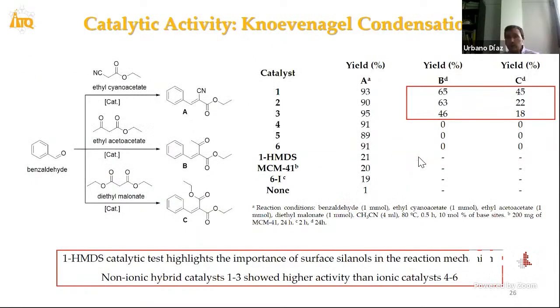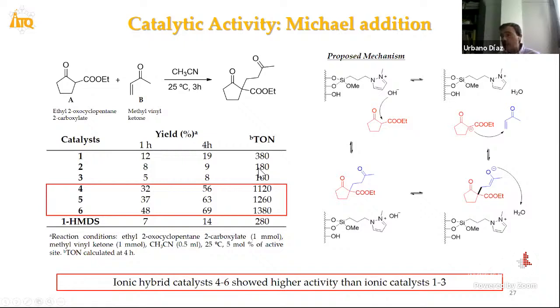The catalytic activity was tested for this type of base hybrid materials, confirming that the non-ionic hybrid catalysts exhibit very elevated yield and conversion in this type of Knoevenagel condensation, depending also on the methylenic group used as substrate, and identifying the importance of surface silanols in the reaction mechanism. Also, in this case, the ionic hybrid catalysts are very active in the Michael addition. In both cases, ionic or non-ionic hybrid catalysts, the mechanisms of the reaction are completely different.